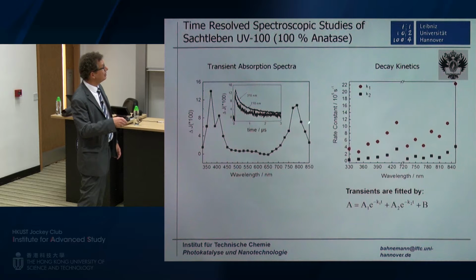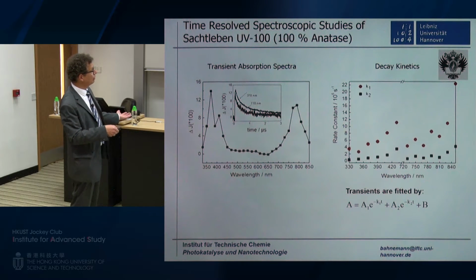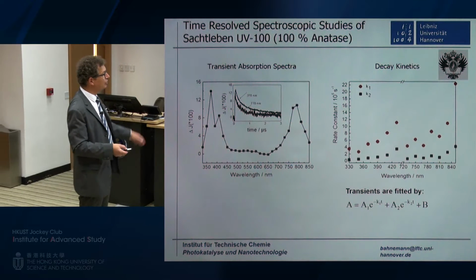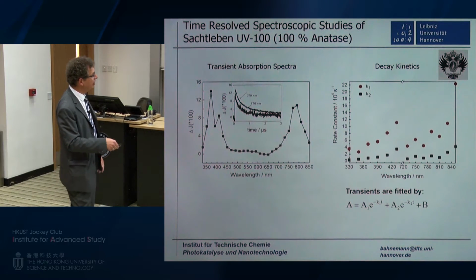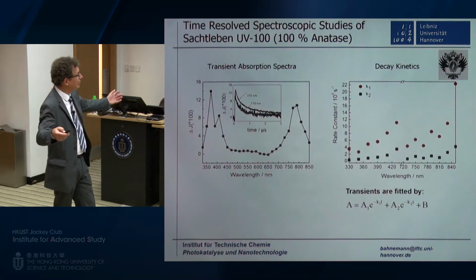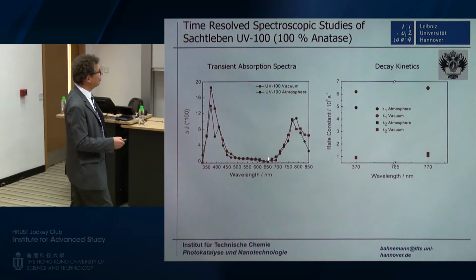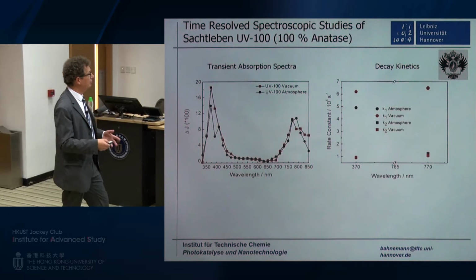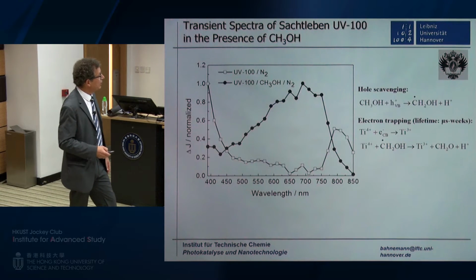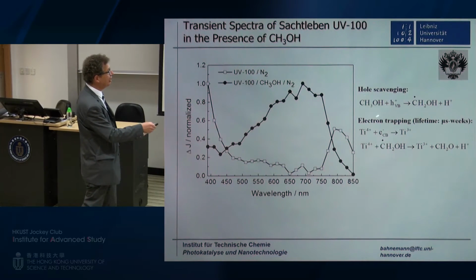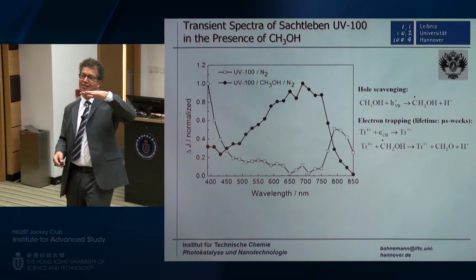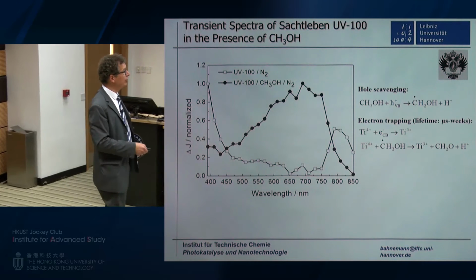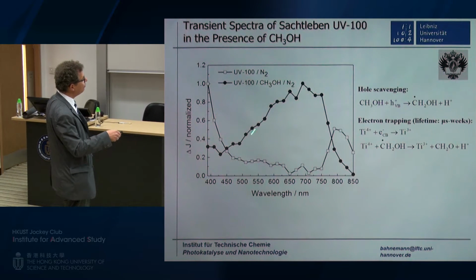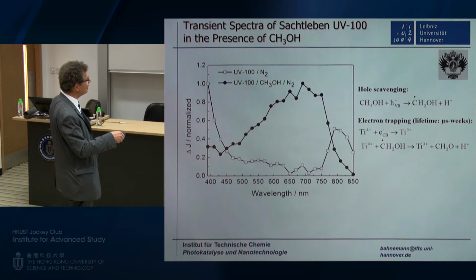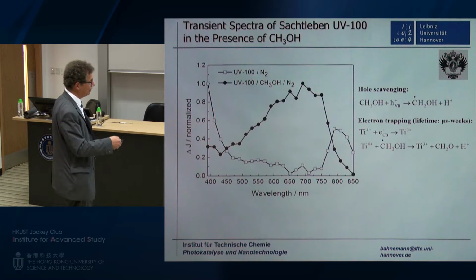We find an interesting thing when we do this. We find the spectrum which resembles the hole spectrum, but we don't see any trapped electrons. There's nothing to react with, so where are the electrons? We don't see the electrons. We can look at the decay kinetics, different decay kinetics, a bi-exponential fit seems to work, but nothing of what we see comes from the electrons. No matter whether we have vacuum or atmosphere, we don't see electrons, we only see trapped holes. Yes, we see electrons, but only if we put in a hole scavenger. Our old friend methanol, now put as methanol vapor on top of our commercial TiO2 powder. Then we see the spectrum of the electrons and no more spectrum of the holes. But when we see the holes, we don't see electrons.